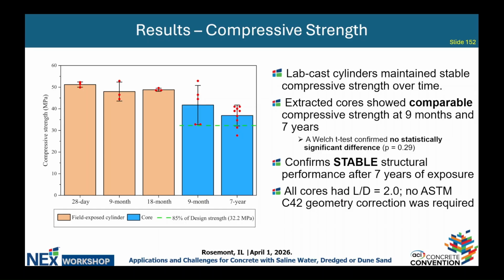Let's start with the results. First, the compressive strength result. We have two types of cylinders. The first type is the cast-in-place cylinders exposed to the same condition as the test block. And we have also extracted cores. For the cast-in-place cylinders, we have them up to 18 months, and they showed comparable performance in terms of the compressive strength value. The error bar here is related to one standard deviation, okay? And those dots relate to the data points.